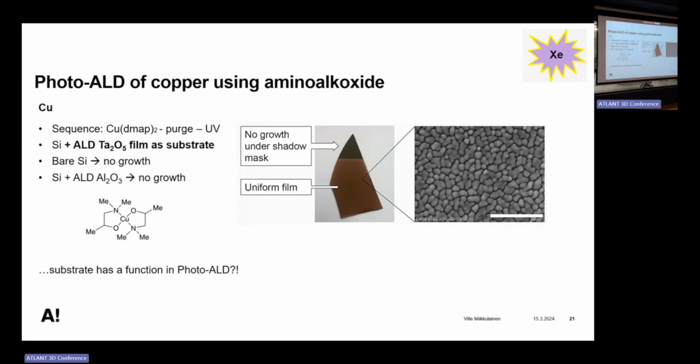At what sort of film thickness did you get pure film closure? Good question. To get all these gaps sealed, I think it requires as high as 5,000 photo ALD cycles. The thickness is then around maybe 70 nanometers, depending on where on these humps you count.